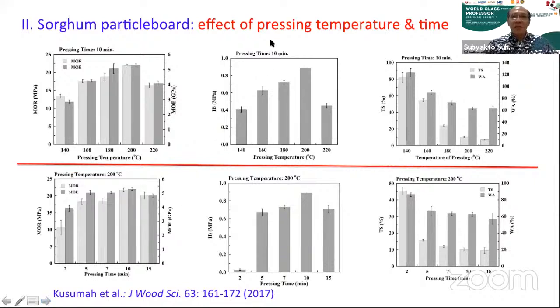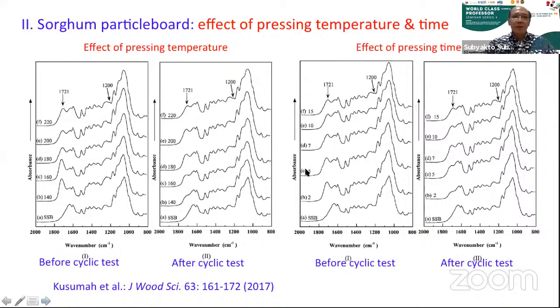And the second experiment, the effect of pressing temperature and time. The upper one is the effect of pressing temperature, and the lower one is the effect of pressing time. And we can see here that 200 degrees C is the optimized pressing temperature. And also for the time, we can see that 10 minutes is the optimum pressing time. And this is the FTIR of this. This is the effect of pressing temperature, and this is the effect of pressing time. Again, we see here the formation of the ester linkage found here.